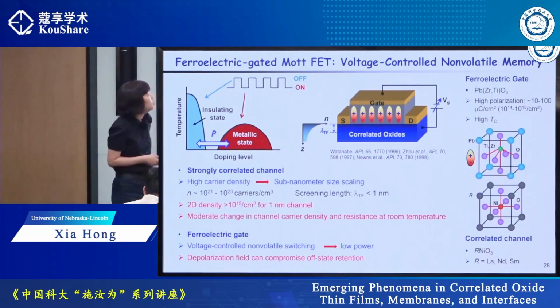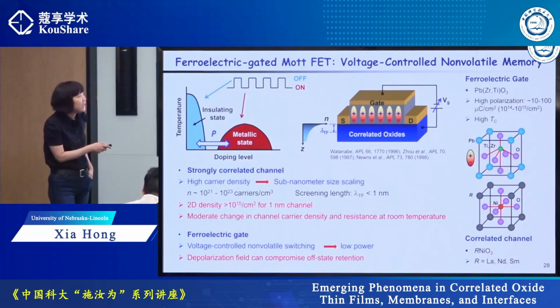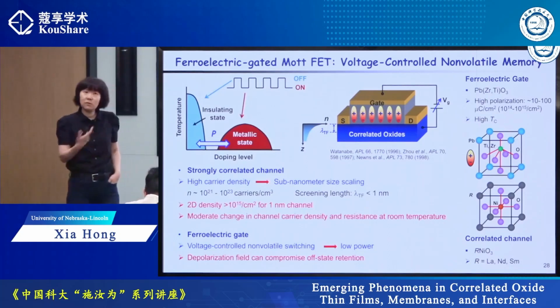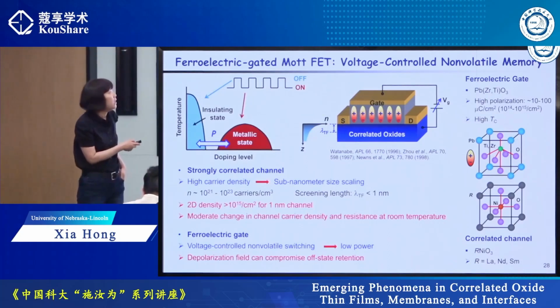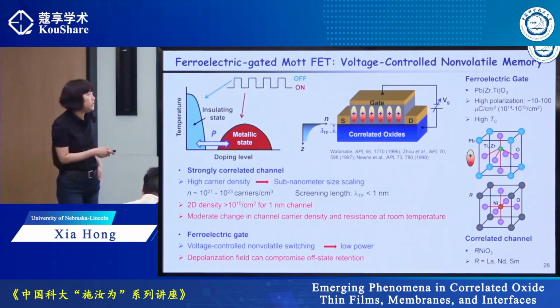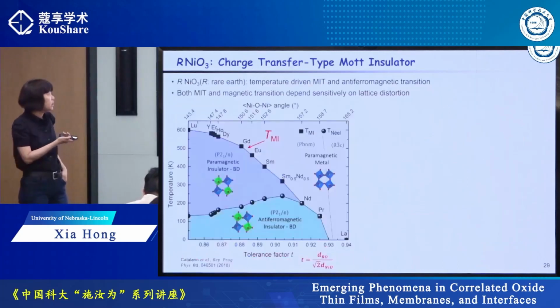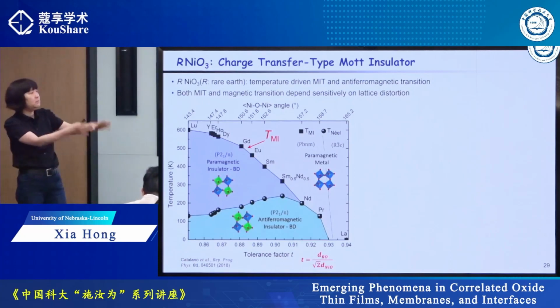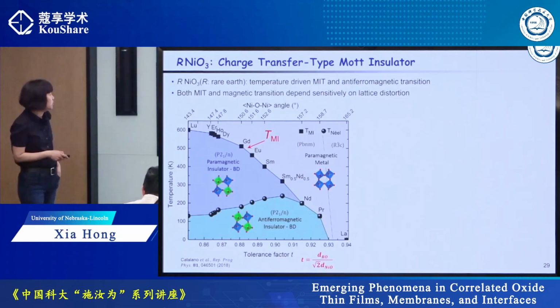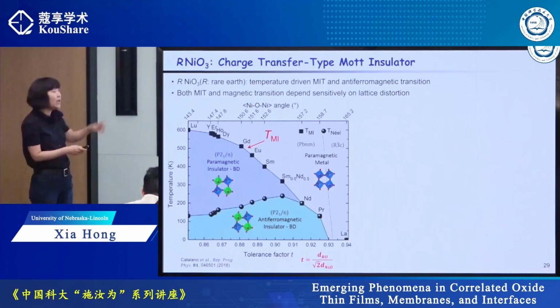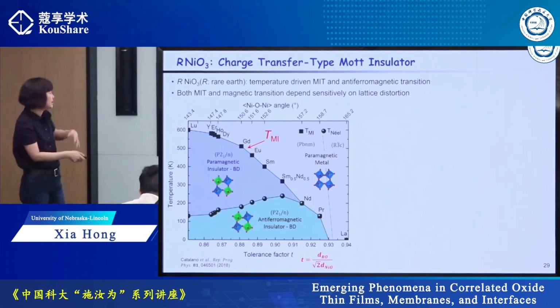What we worked with is a ferroelectric gate, lead zirconate titanate, known to have very high Curie temperature and high polarization field. And for the correlated channel, we work with the rare earth nickelate. Rare earth nickelate is known to have strong coupling between the magnetic state, the electronic state, and lattice distortion. So here is a phase diagram versus the tolerance factor. 1 means you have a perfect cubic. The smaller the number, the more distorted it is.